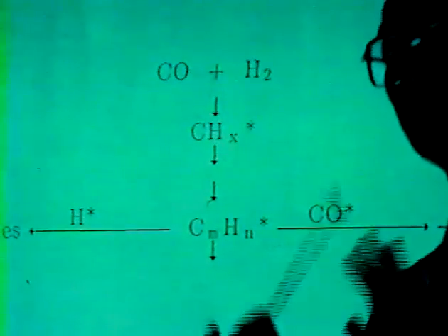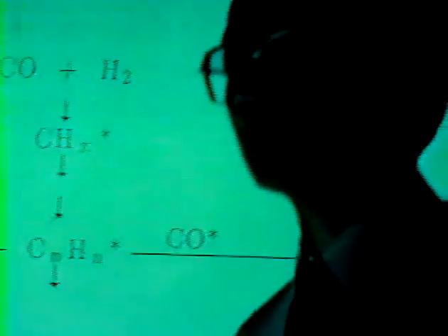In this regard, you have to remember that the conventional Fischer-Tropsch catalyst require very small amount of promoters, usually less than 1%. On the other hand, in order to be an effective alcohol synthesis catalyst, you require large amount of promoters, usually more than required for complete coverage of the surface.